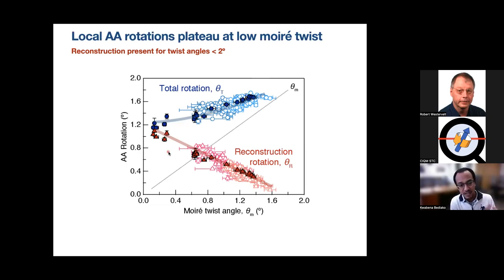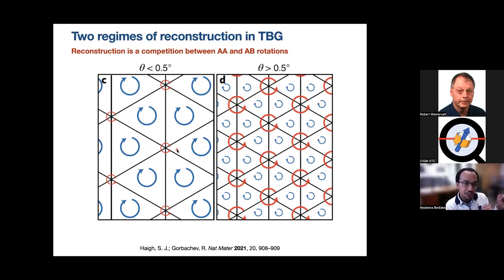And I don't have a lot of time to get into the implications of these rotations for the physics of twisted bilayer graphene. But I'll summarize and say that, because I want to tie this back into what we're seeing in chemistry, because some of you might be wondering, how does this all matter for the electrochemistry I was showing, and I will get there. But I just want to emphasize that what we find is that there are two regimes of reconstruction in these twisted structures. It's not just that the reconstruction relaxation turns on below a degree or so, or 0.8 or so. It's actually that there are two regimes of relaxation, and there are two competing rotation processes. One wins out at larger angles, at about 1 degree or above 0.5. The other wins out at lower angles.